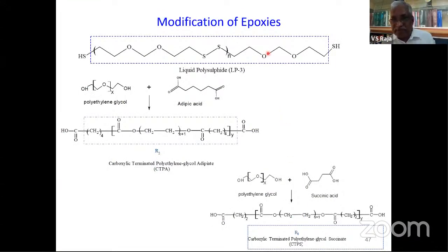We borrowed something from the aerospace industry, where people use polysulfide, right? Polysulfide is a linear chain, an elastomer, for example. It is used as a gasket and so on. So can we incorporate this polysulfide into the epoxy? Can we incorporate carboxyl-terminated polyethylene glycol adipate? We synthesize this particular CTPA. We synthesize again carboxyl-terminated polyethylene glycol succinate. We synthesize these compounds and then we cross-link them along with the normal epoxy.